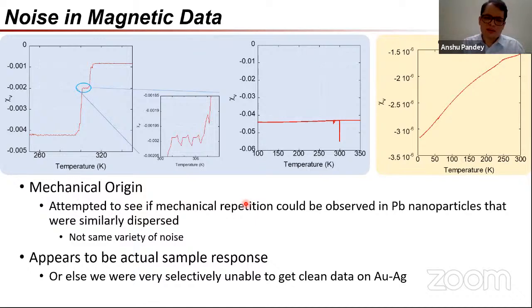So with that thought, we decided, well, if this happens because of mechanical reasons, we should be able to replicate a similar ligand environment for other nanoparticles like, say, lead, and try to see if we got the same variety of noise. The answer was we do not quite get the same variety of noise. We do get some repeats in lead, but not the same varieties. It became debatable in our minds whether that's what's happening. The second, more interesting point was that there are other forms of noise which we also found in our materials which we don't understand. For example, these sorts of repeats which have absolutely no business being there. We also find peculiar spikes in our data which accompany the diamagnetic state.